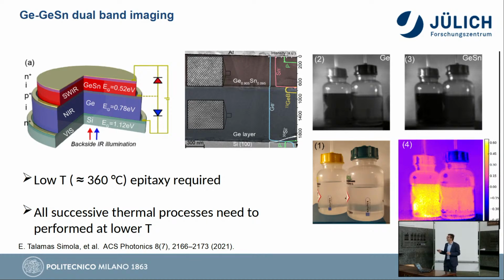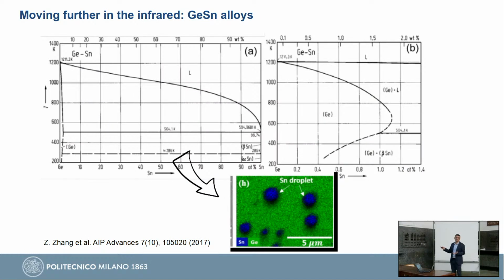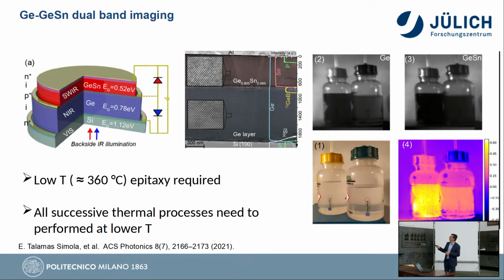Now the problem is that if you then have to heat up your system, for example, for making contacts or for any other process, you will get back to this situation. So thermodynamics will claim its place, and you will again form tin. So the idea is, can we move this process of forming germanium tin later in the fabrication and have it only where we need it? So if I need just a few square micrometers of germanium tin, can I make it locally?